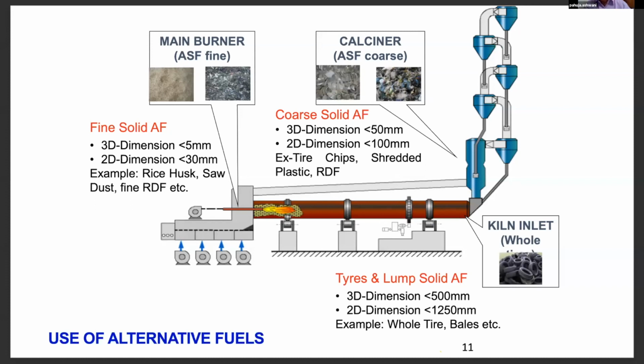And shredded tires can be fired at the calciner, and the lump whole solid tires can be fired at the kiln inlet also. This practice of firing whole tires in the kiln inlet is generally not prevalent in India. Generally, the firing is mostly done at the calciner inlet by most plants. In very limited cases, the alternate fuel firing is done at the main rotary kiln burner because the quantities handled are very small, and the first priority is to put all the alternative fuels in the calciner itself, which is easier to handle.